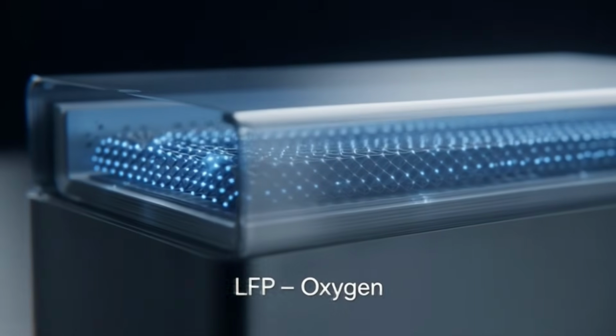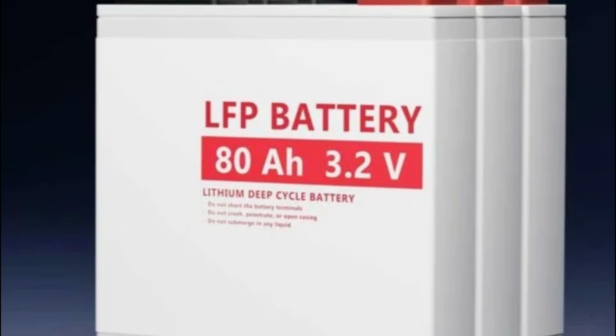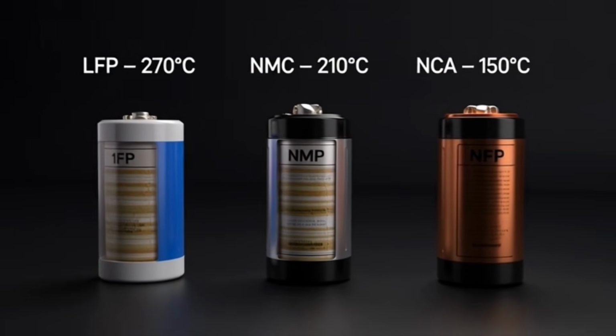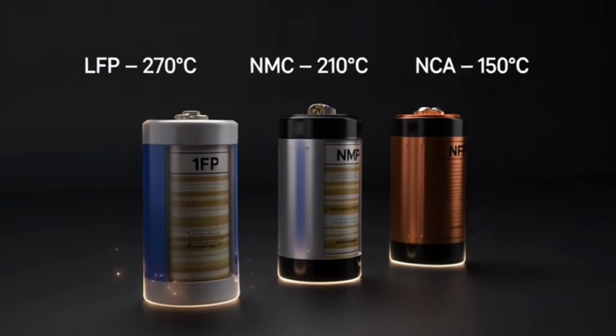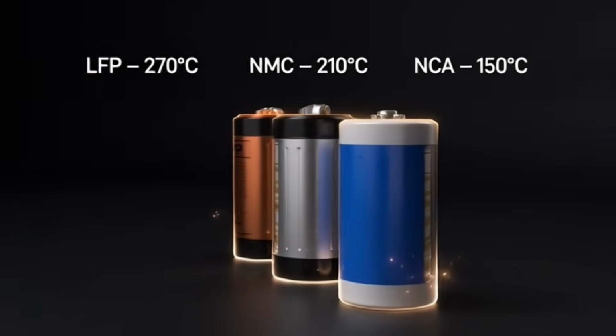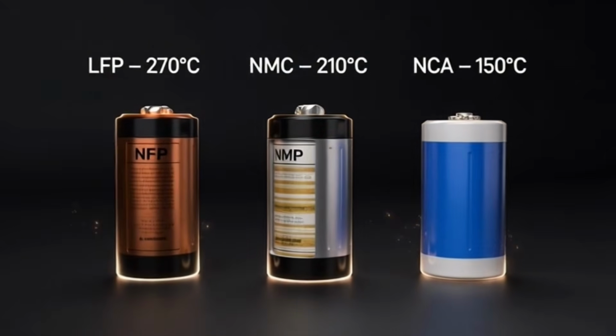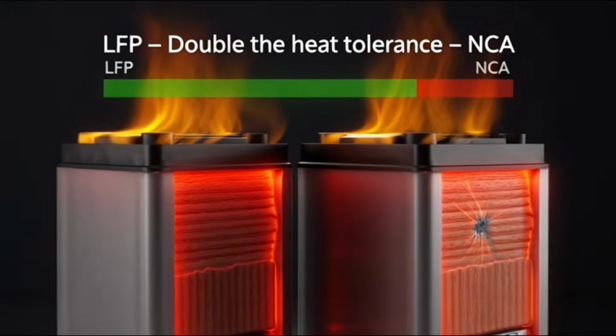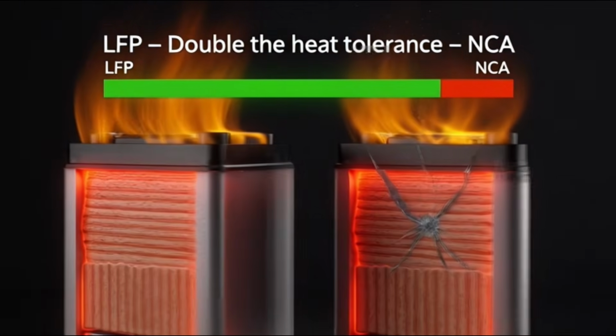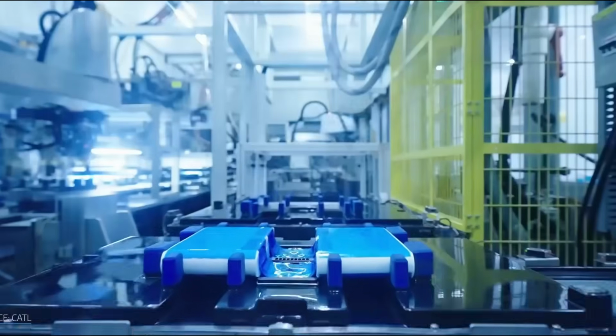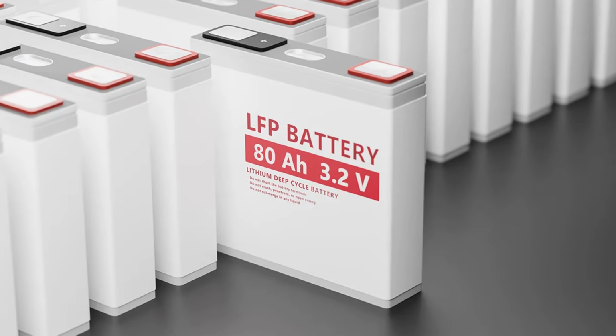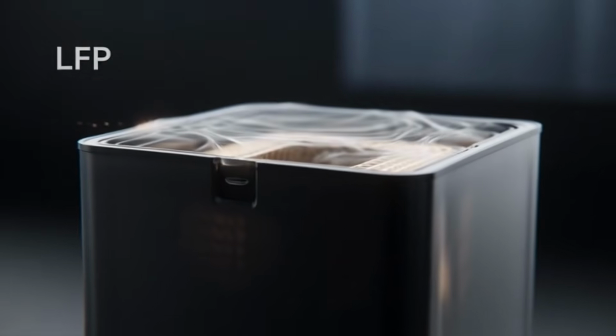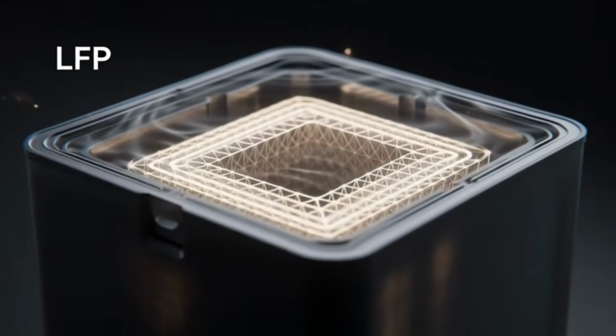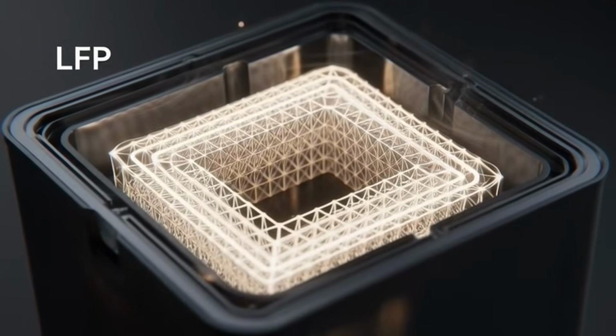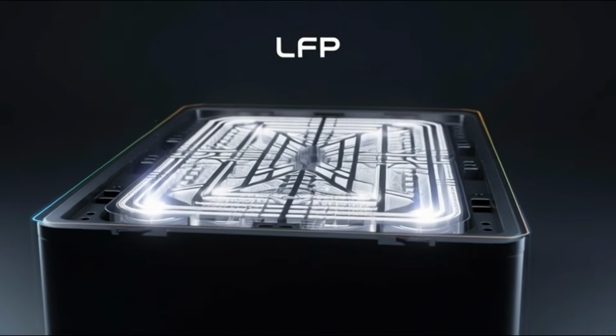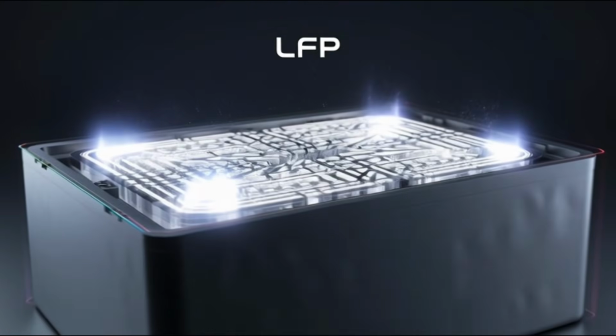The temperature stays controlled. This is why LFP batteries have a thermal runaway threshold of 270 degrees Celsius, compared to 210 for NMC and 150 for NCA. That's not a small gap. That's nearly double the heat tolerance of an NCA battery. In practical terms, LFP batteries are dramatically safer, dramatically more resistant to the kind of gradual heat damage that silently kills battery capacity over time, and dramatically less likely to fail in a worst-case scenario.